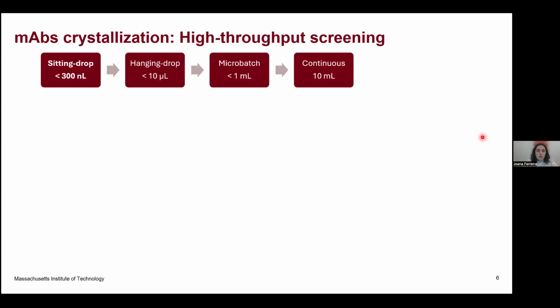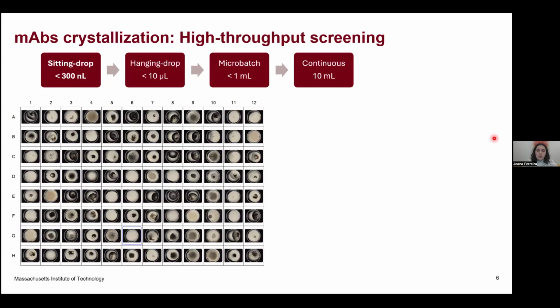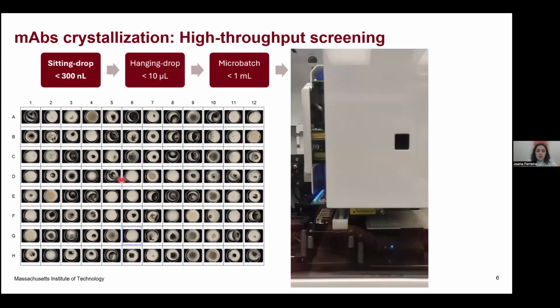So for the screening part, we start at a very small scale using sitting drop, just less than 1 microliter. Then we go a slightly larger scale using hanging drop. And then our idea, because we want to reach a continuous process, we go through microbatch and then eventually crystallizing in continuous. So here is one example of an outcome from 96 different conditions. And we can run thousands of conditions using,